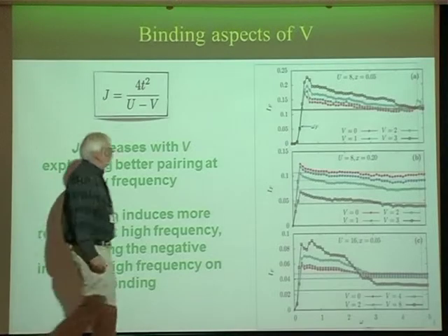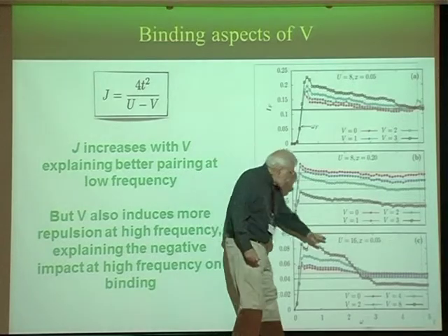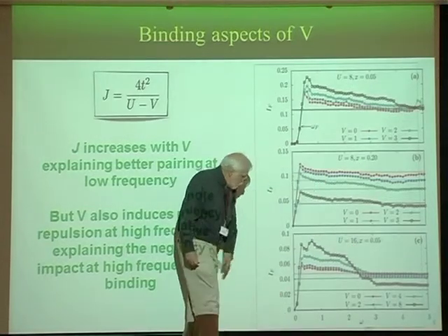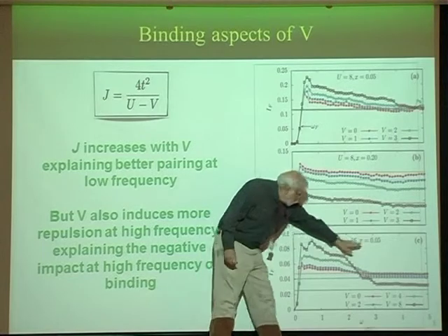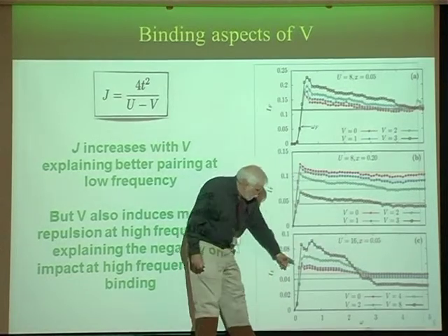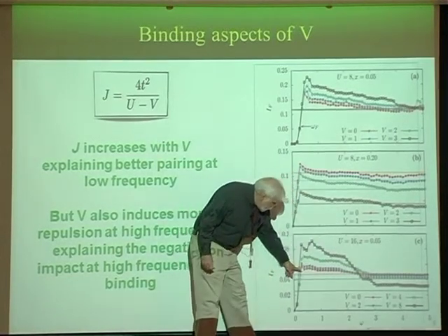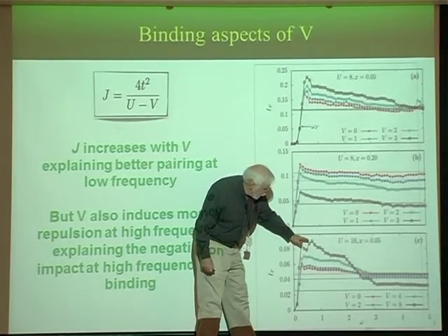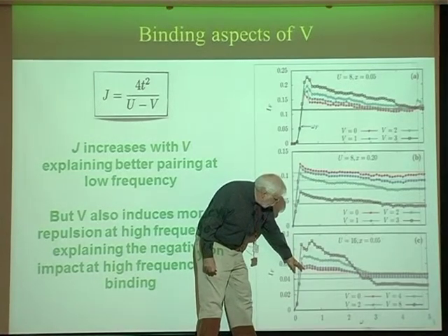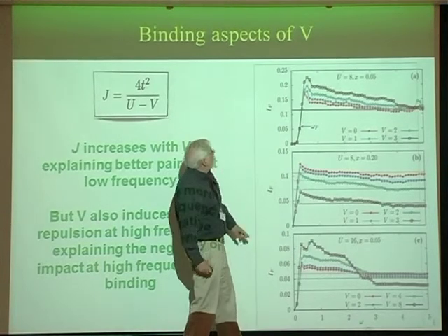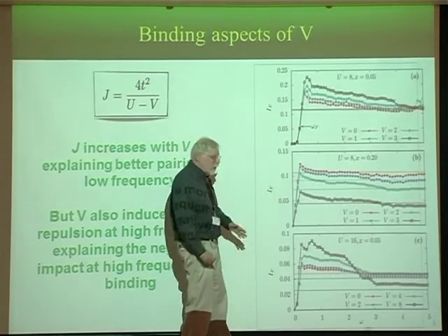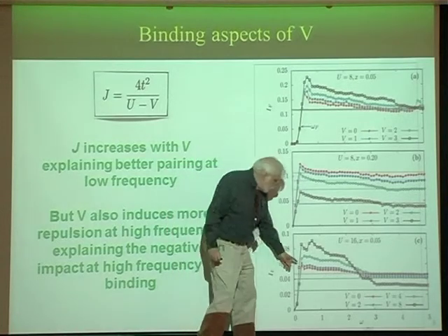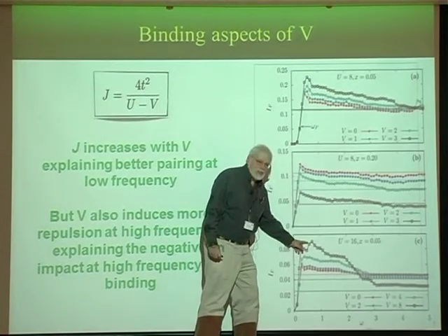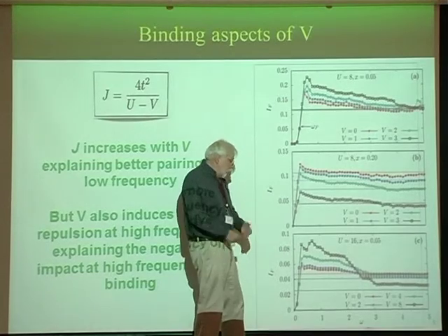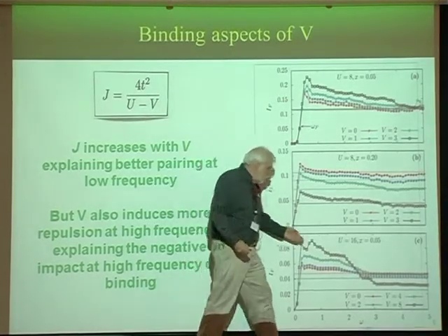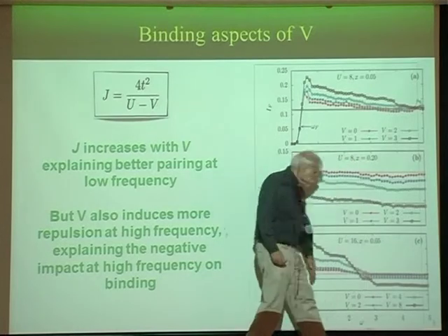So we can look at these curves again and see, for example, that at U equals 16, then for V, this is underdoped, x equal 0.05. You see that at V equals 0 and V equals 8. So in going from V equals 0 to V equals 8, you change 4t squared over U minus V by roughly a factor of 2. And you see that this goes up by roughly a factor of 2. But yet, at high frequency, V is doing its thing, so it's killing this much more.